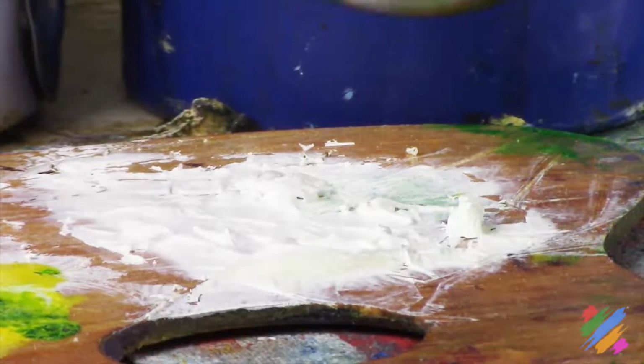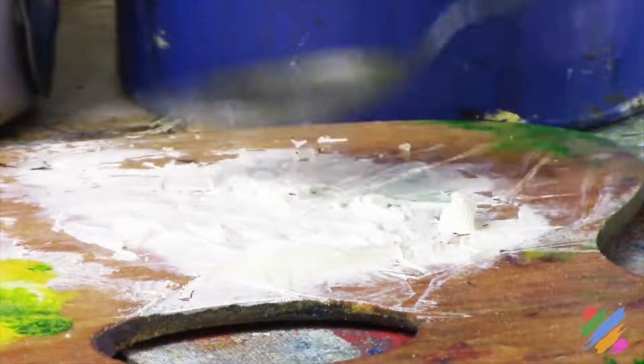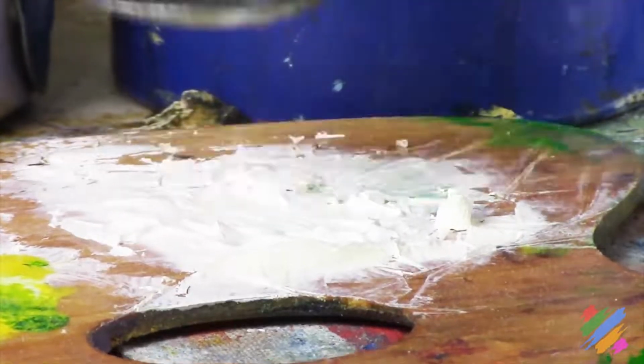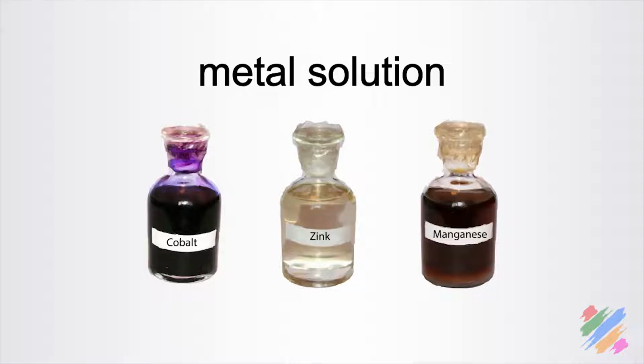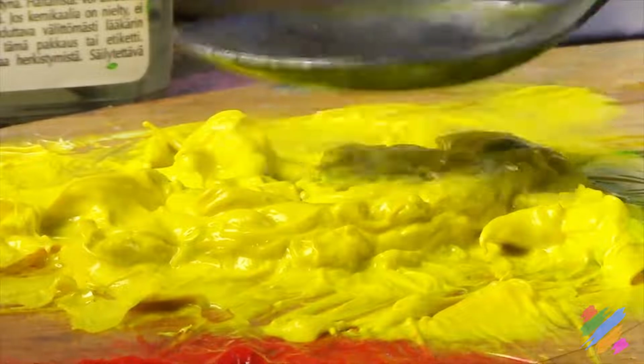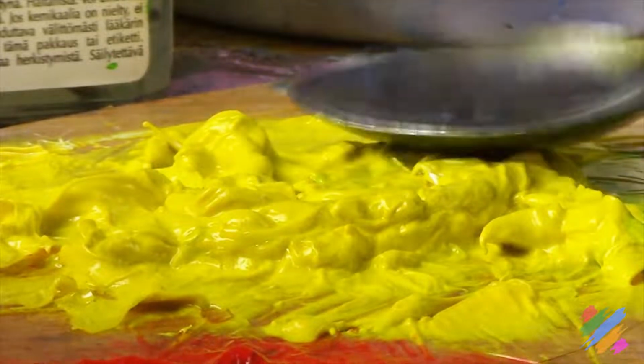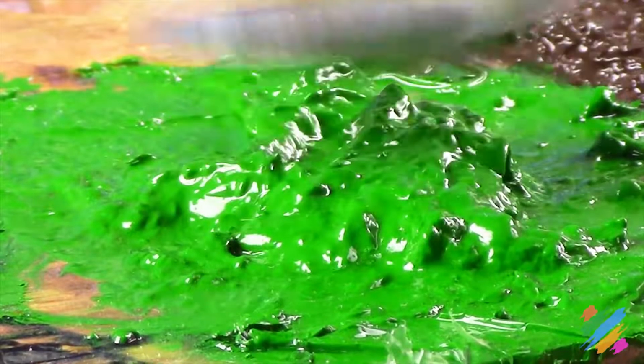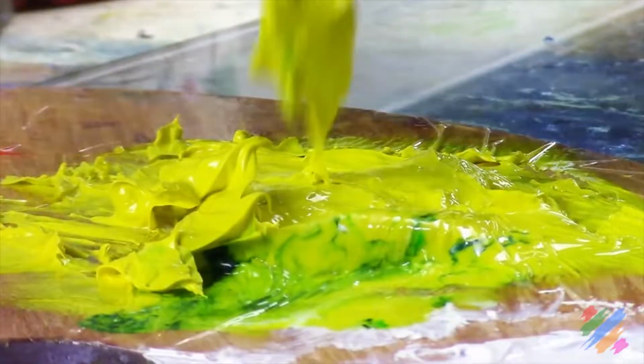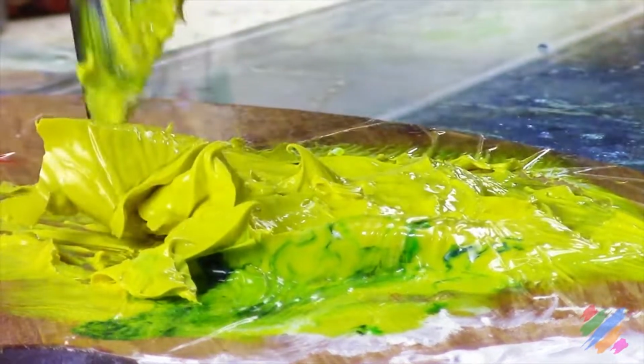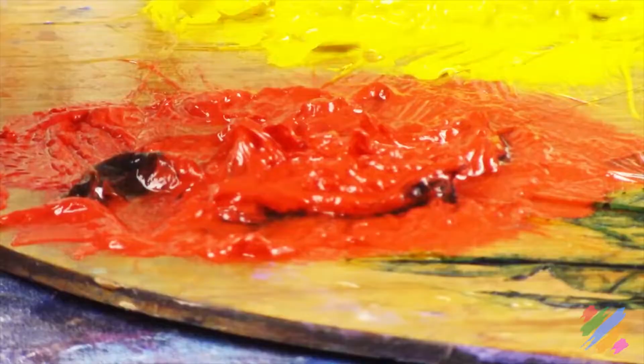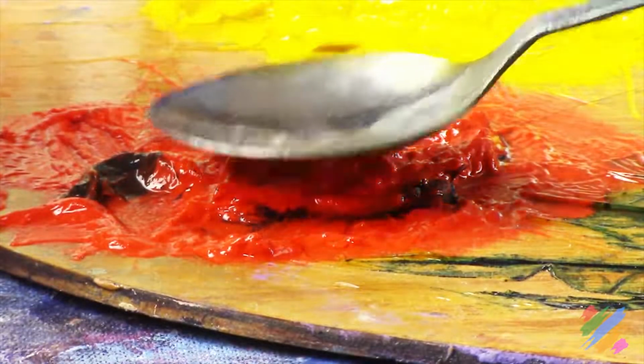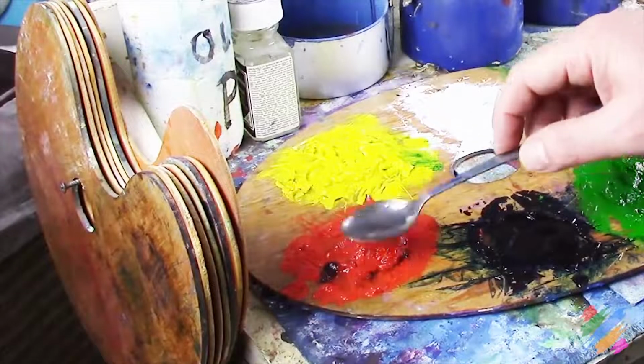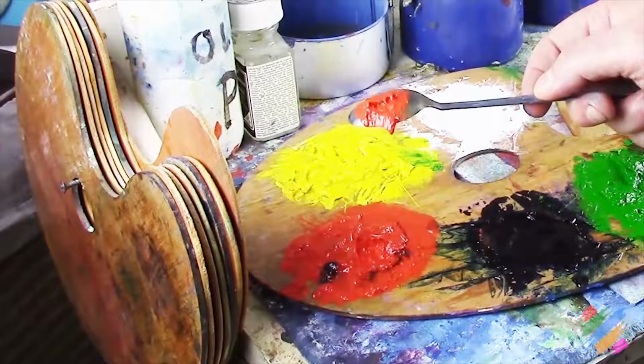Let's see, for example, what happened to these palettes that we prepared 10 days ago. The white is pretty solid, and we could expect this because this pigment has a very high concentration of zinc and titanium, which are both metals. Let's see now the other colors. As we can see, outside they are covered by a gummy but solid layer, while inside they are still fluid. But if we check the red, we can see that it's still completely fluid, even after 10 days.